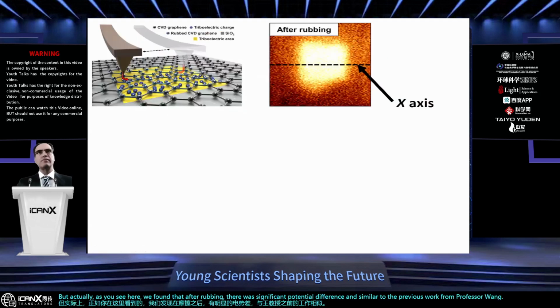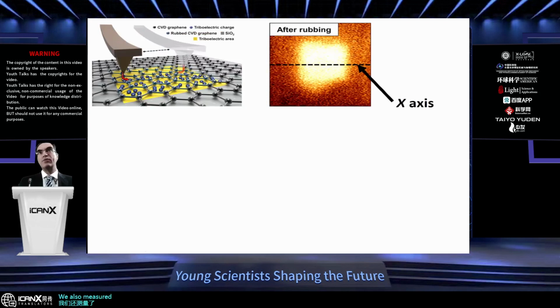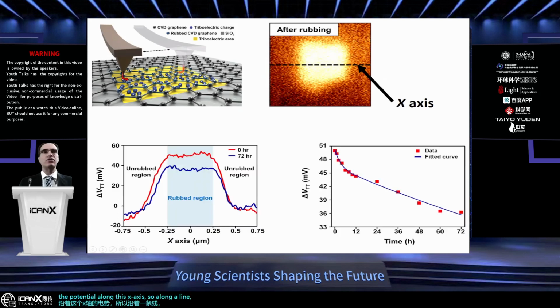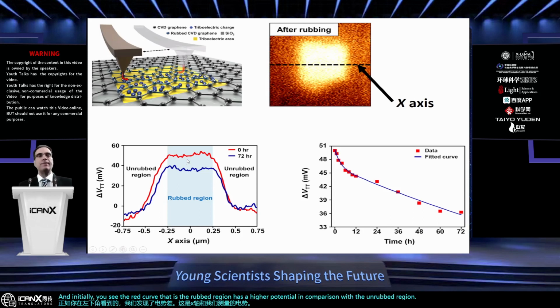So what happened? We also measured the potential along this x-axis, so along a line. And as you see here at the bottom left figure, we found the potential difference. So this is the x-axis and the potential that we measured. Initially, you see the red curve, that is the rubbed region, has a higher potential in comparison with the unrubbed region on the periphery. But after very long times, here, for instance, after 72 hours, so much longer than in the previous experiments by Professor Wang and coworkers, we still found significant potential difference.